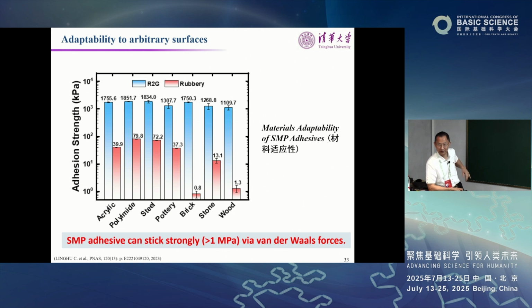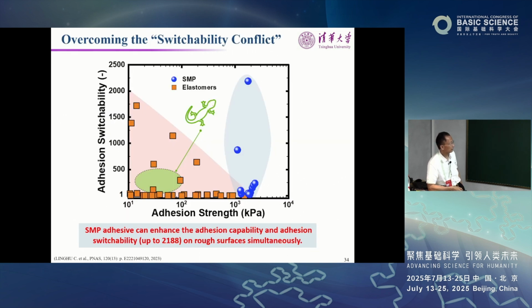The true reason is that it basically uses van der Waals force. You press it, you cool it down, right? This van der Waals force is pretty stable and highly adaptive to arbitrary surfaces. As for the switchability, because of the shape memory effect, the energy is not lost; it's stored in the interface. You can release it, right? So in phase transition adhesion, you no longer have the conflict with switchability. This is the traditional material, but if you use phase transition, these two become completely decoupled. You can have high strength, but the switchability can be designed completely decoupled.